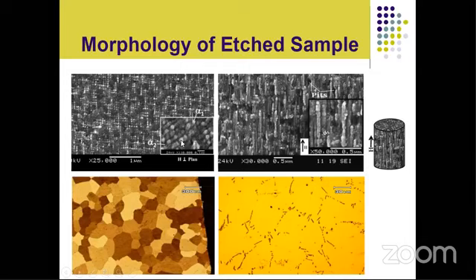And this is the alpha 1 phase. The bright portions are the alpha 1 phase, and the region between the bright portions is the alpha 2 phase. So the alpha 1 phase, which is magnetic and iron and cobalt rich, is separated by the non-magnetic phase. So we have countless alpha 1 and alpha 2 regions in our material, and these phases actually define the coercivity and the other magnetic properties of the alloys.